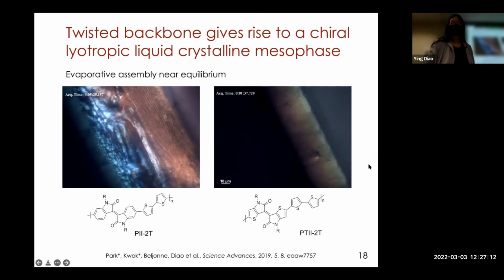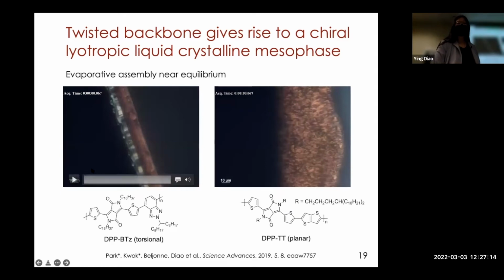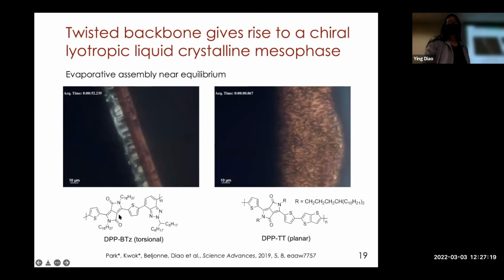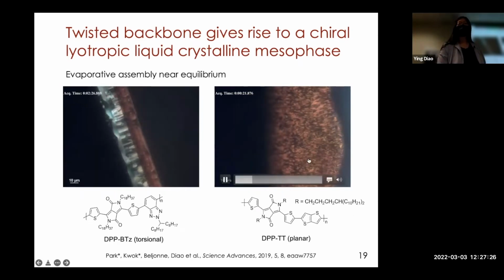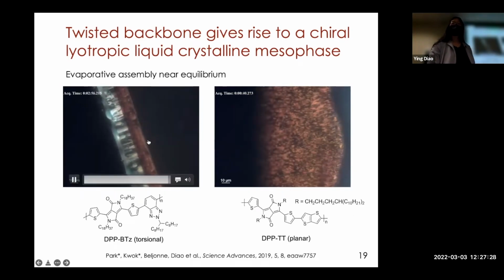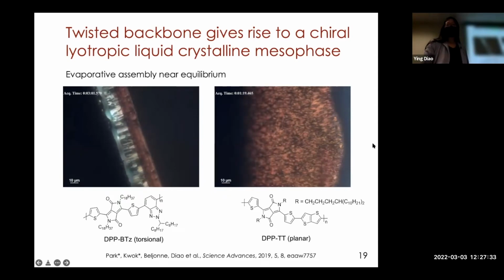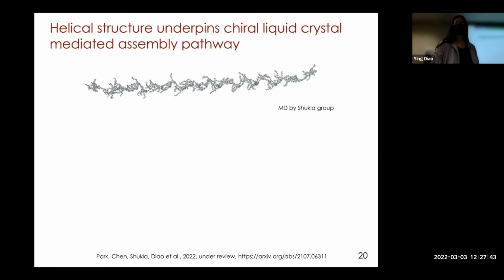And we observe this phenomenon again using another pair of polymers based on diketopyrrolopyrrole. Again, the twisted polymer goes through a chiral crystal phase, whereas the achiral polymer bypasses the crystal phases. You can see that the texture of the films are really different, as well as the properties in the end. So what's intriguing is how chiral polymers can give rise to chiral structures. We determined that what underpins chirality is the helical structure.